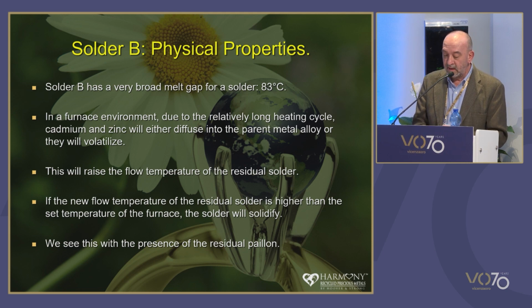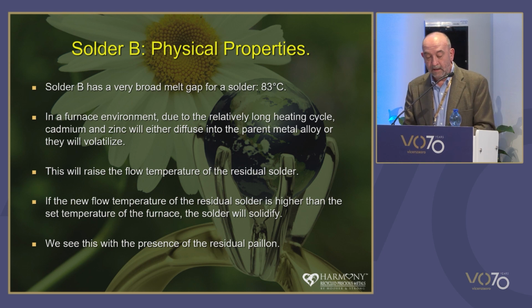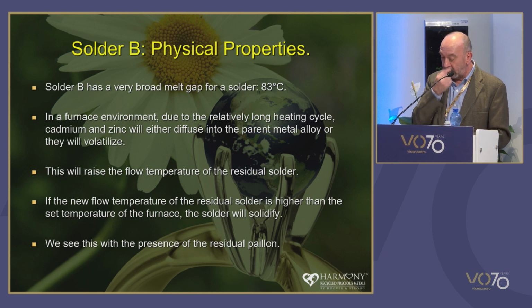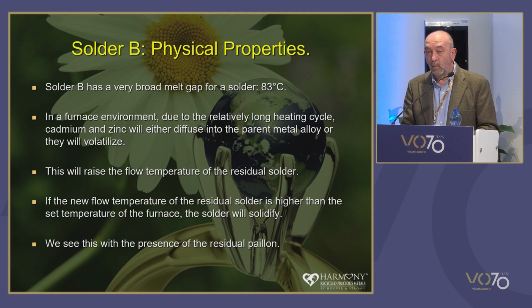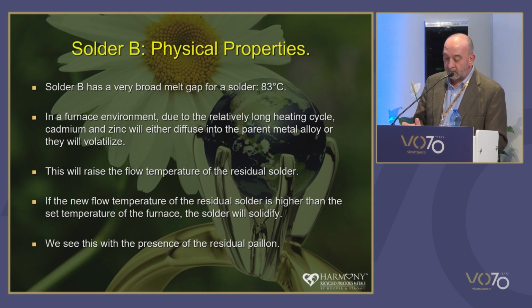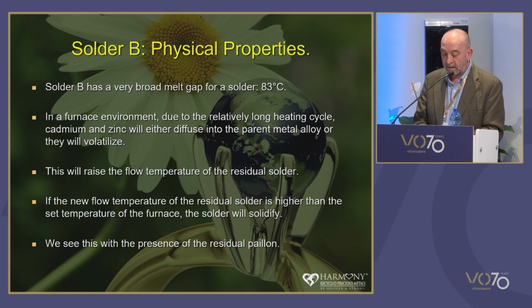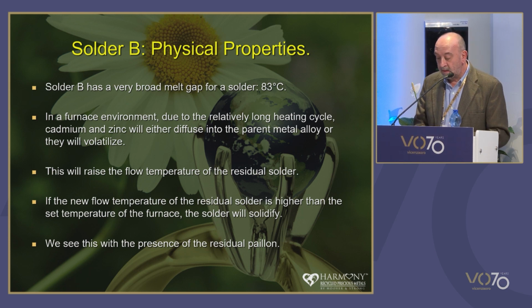So both cadmium and zinc are included in this solder alloy to lower the melt temperature. In this case, the potential is there for either one or both to diffuse into the parent metal or just to volatilize off and change the composition of the solder that you've got left. Either mechanism will result in compositional change over a period of time in the furnace and will result in an increased melt and flow temperature for whatever solder is left. The new melt temperature or flow temperature of the solder might be raised sufficiently so it's above the set point of the furnace, so it's no longer going to melt or perform as intended. And that's probably why we see the residual paillon on the furnace soldered test.